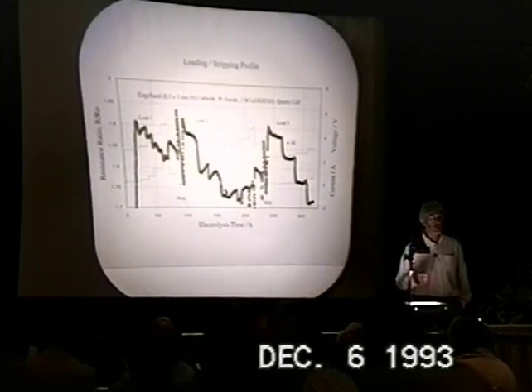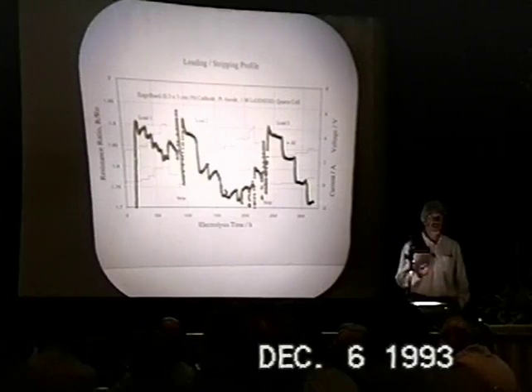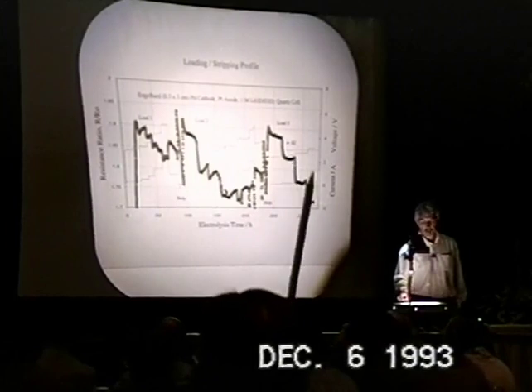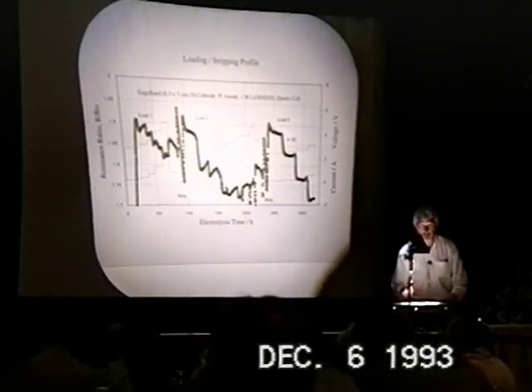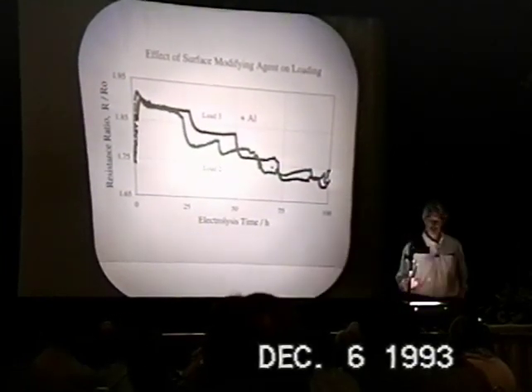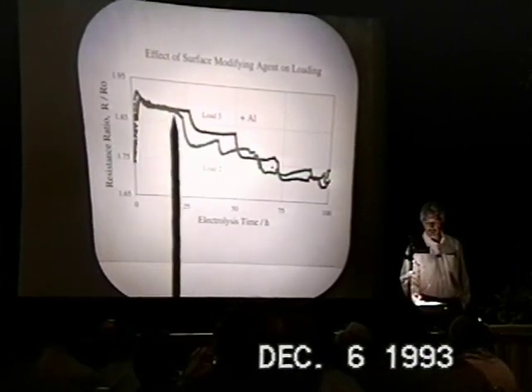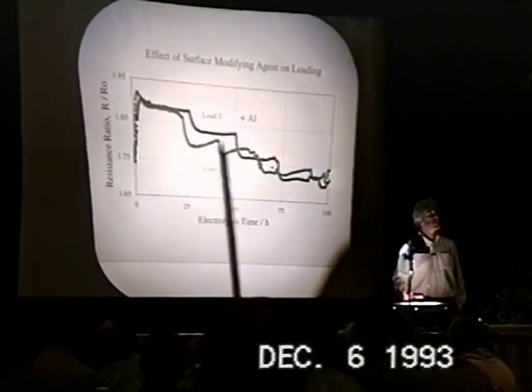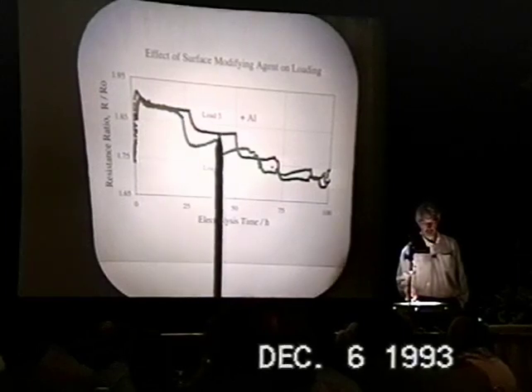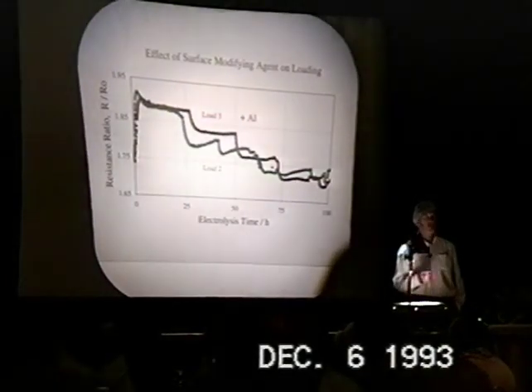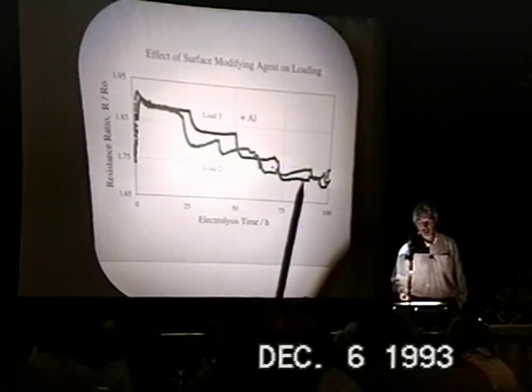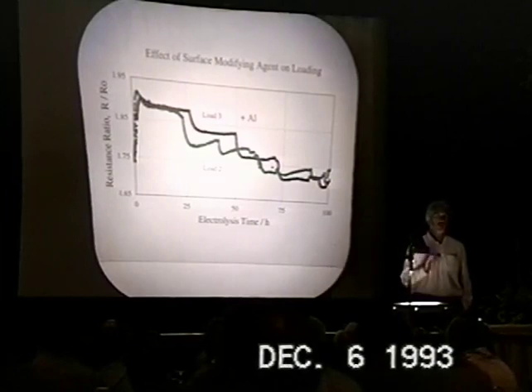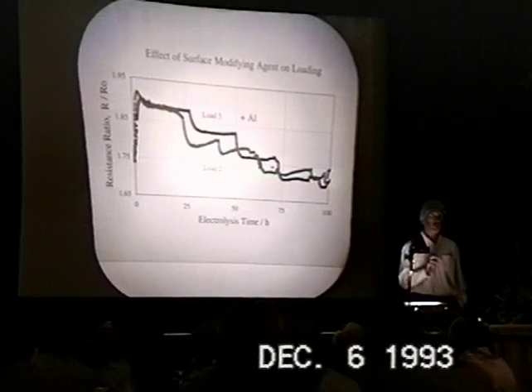The addition of aluminium doesn't necessarily improve the loading instantaneously, but it protects the cathode against deloading with time. Alan has taken the data in this set and superimposed them on the data in this set, the second and third loadings. You can see them overlaid here, so that load 2, no aluminium, as the current was increased, the resistance ratio decreased, that's good, increases, that's bad. With the addition of aluminium, identical current steps, the apparent, the immediate increase in loading is possibly even worse with aluminium additions. But what it is that these don't deload spontaneously with time. So aluminium is doing something on the surface to prevent whatever surface modification occurs with time, which leads to deloading.